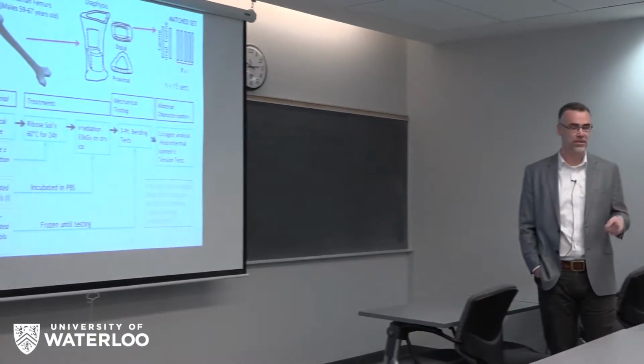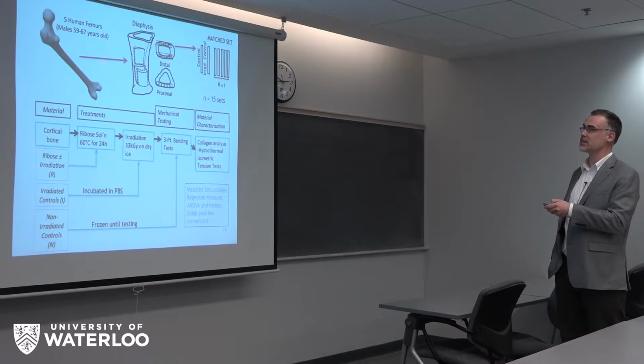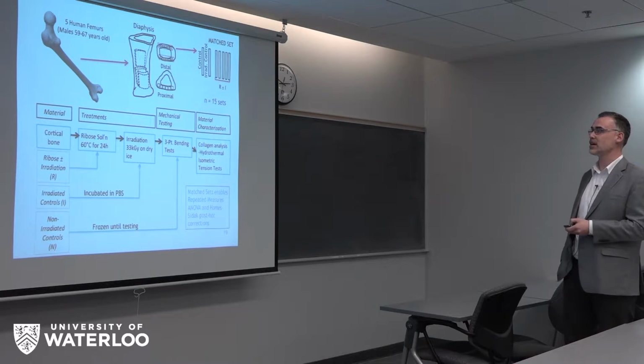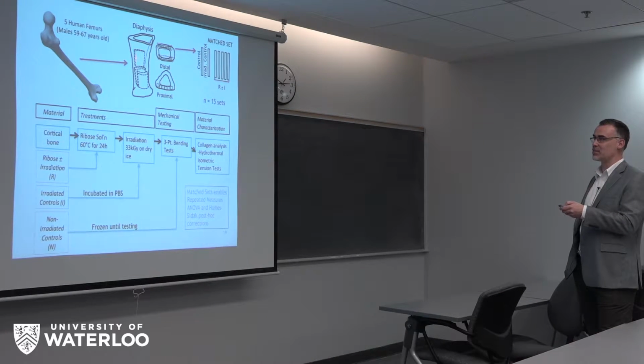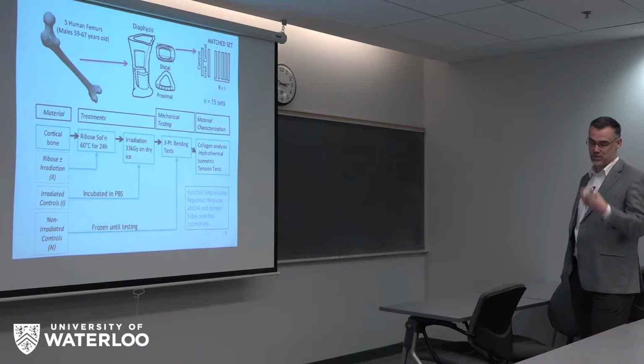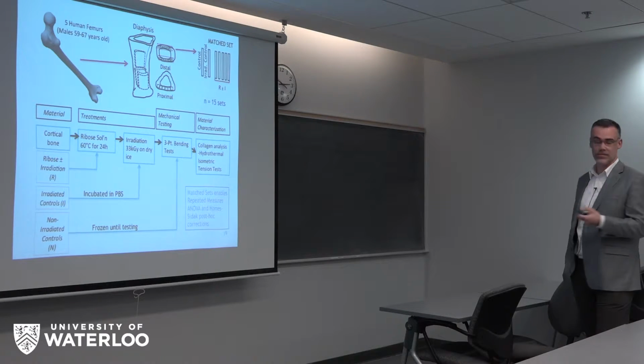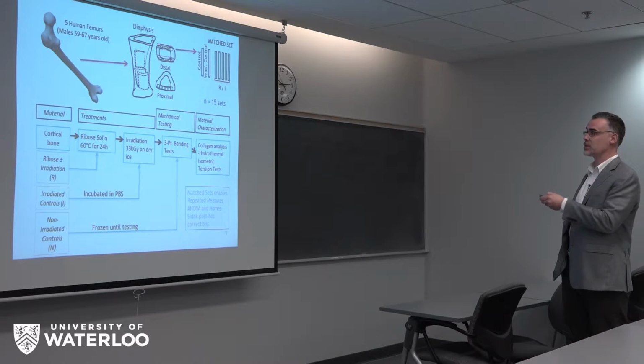So the benefit of working in a hospital and one with a tissue bank is you can ask them to be collaborators, or it was kind of a mutual thing, because they wanted a solution to this problem or would like to know if it was possible. And so they donated us human femurs, and we used males to control for things like osteoporosis. And then from the shaft, we were able to cut out portions located anatomically, and then in each plate of bone that we're cutting out of the cortex, we would produce adjacent beams called a match set, and within each match set we'd have a control, which was just fresh frozen after being cut, a conventionally irradiated control, and then a number of treatment groups.